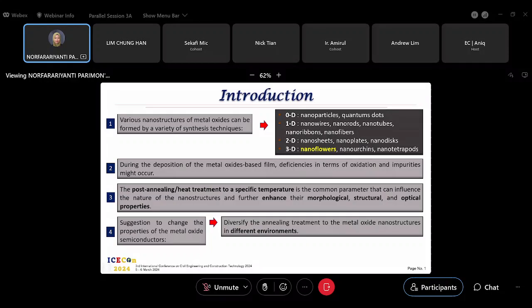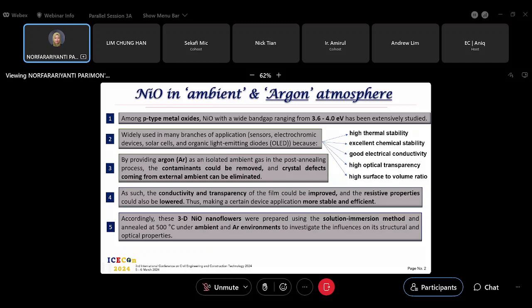well. Normally the heat treatment or post annealing of the sample uses different annealing temperatures, but we suggest to diversify the annealing treatment of these metal oxide nanostructures in different environments using argon and ambient atmosphere. Metal oxide consists of p-type and n-type metal oxide. One of the p-type metal oxides, nickel oxide, has been extensively studied.